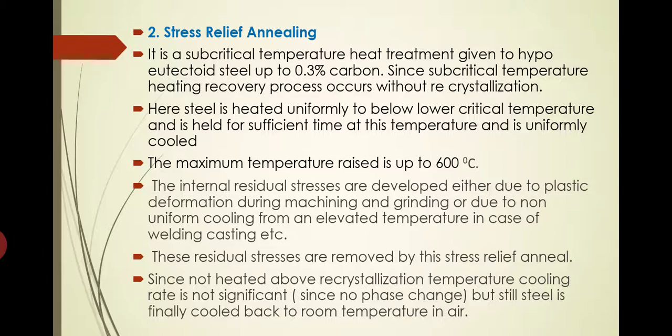Since it is subcritical temperature heating, the recovery process occurs without recrystallization. See, here there is no recrystallization happening since the heating temperature is below the recrystallization temperature or below the lower critical temperature. So only the internal stresses developed will be relieved. Here steel is heated uniformly to below the lower critical temperature, held for sufficient time at this temperature, and uniformly cooled. The maximum temperature raised is up to 600 degrees Celsius.